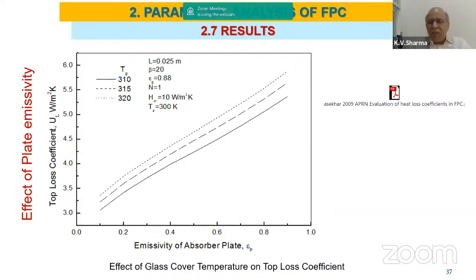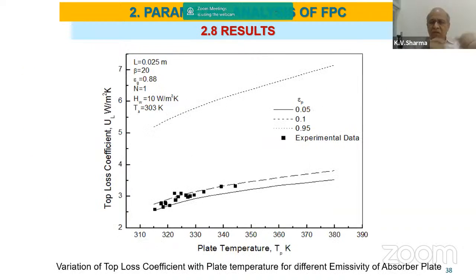So what is the impact of the plate emissivity on the top loss coefficient? When I do a particular analysis, it is quite evident to ask whether my program is correct or not. I am getting some results, but I do not know whether my program is reflecting the true nature of a collector. So I have taken the experimental data of one of the authors available in the literature, and I see that when I vary the plate emissivity between 0.05 and 0.1, the experimental data of some other author is in good agreement with my numerical results. So this gives me confidence that the results which I am presenting are correct.